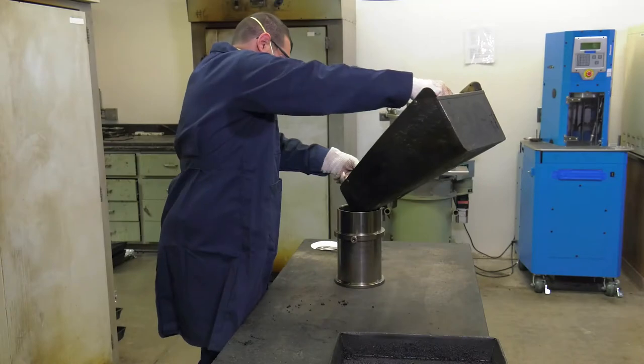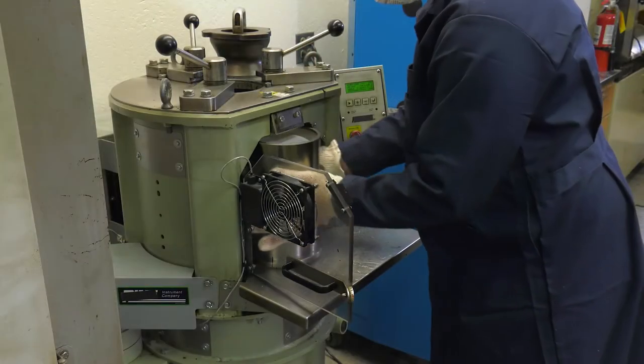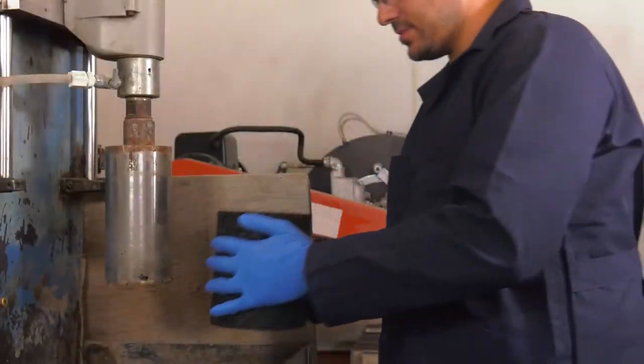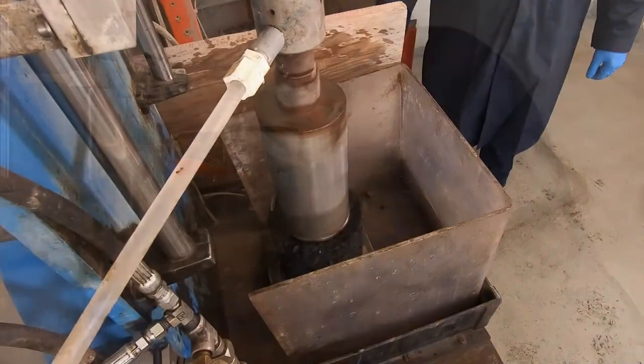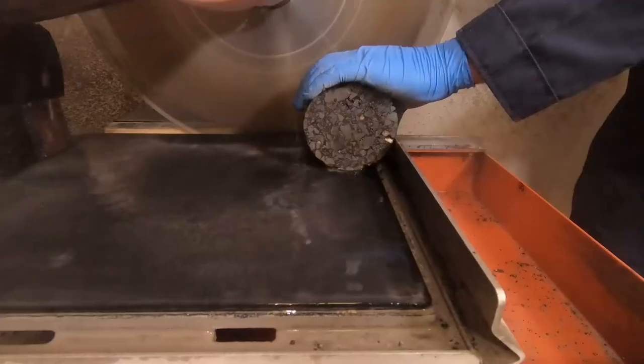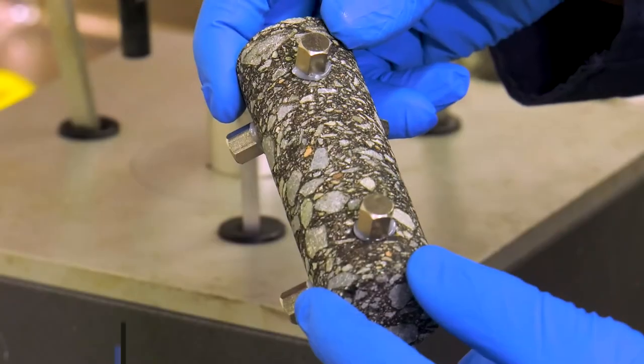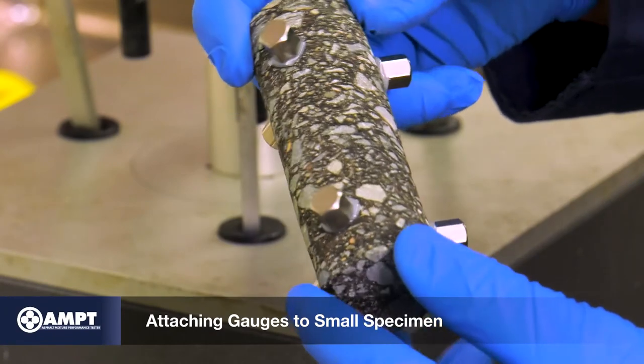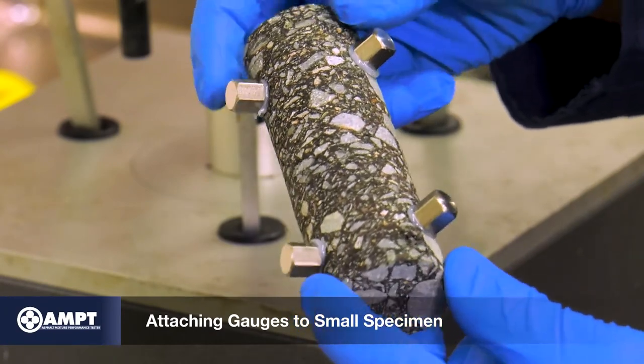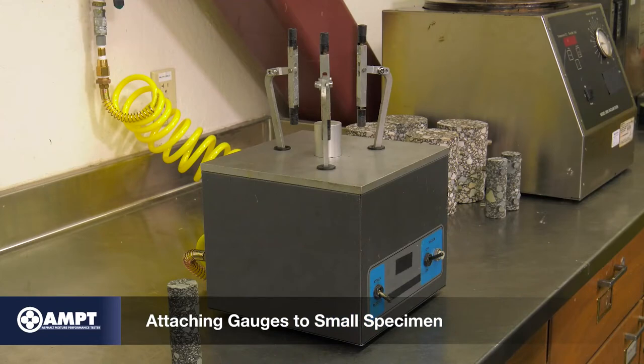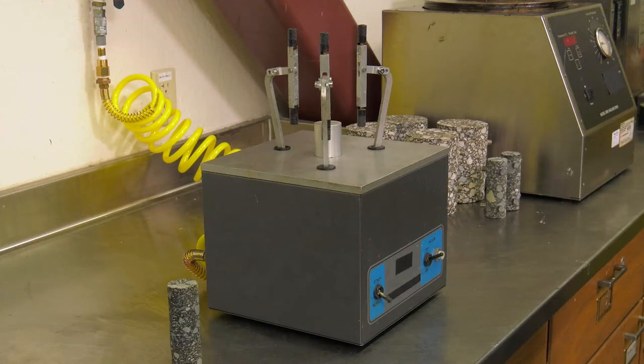Before beginning this test, prepare your test specimen as recommended in AASHTO PP99. Refer to Video 1 in this series for more information. Before beginning the dynamic modulus test on the AMPT, attach gauge points to the test specimen using a fixing jig.